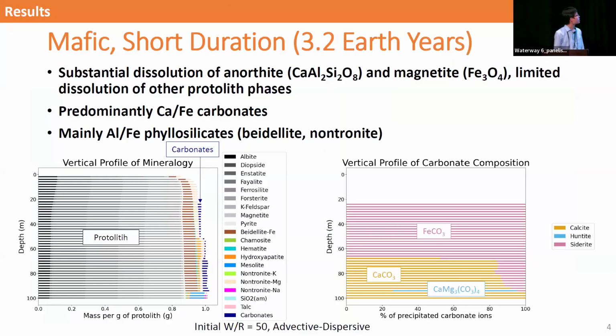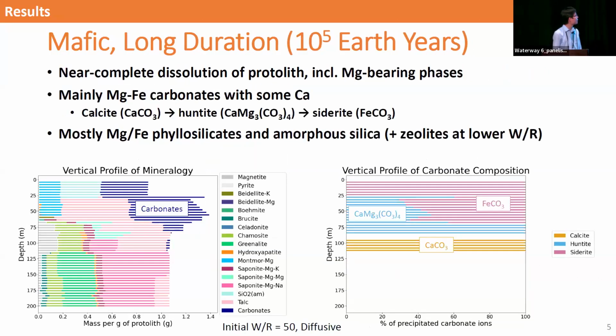Now let's look at the results, starting from the mafic protolith with the short duration of alteration. The figure on the left shows the vertical profile of mineralogy. Of the protolith phases, anorthite and magnetite were substantially dissolved, but other phases only had limited dissolution. The figure on the right shows the carbonate composition, and they were predominantly calcium iron-rich carbonates, and the carbonates were mostly associated with aluminum or iron phyllosilicates.